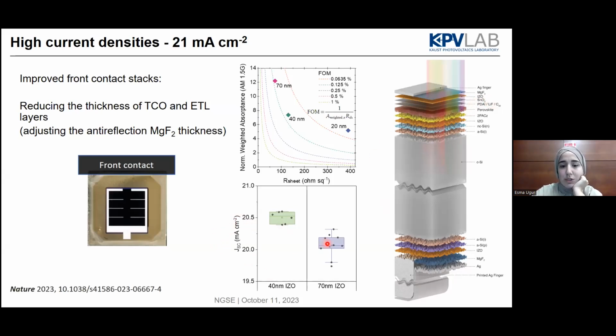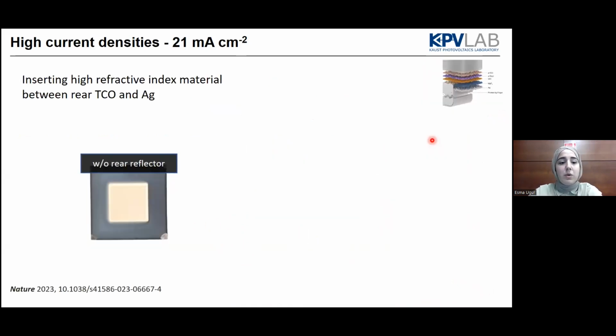That leads to really higher current densities, but now we also have to deal with the bottom part of the device, because when we are enhancing the top part, we need to catch the current matching condition for those ones, because we were for sure getting higher current densities from the perovskite side. So for that one,